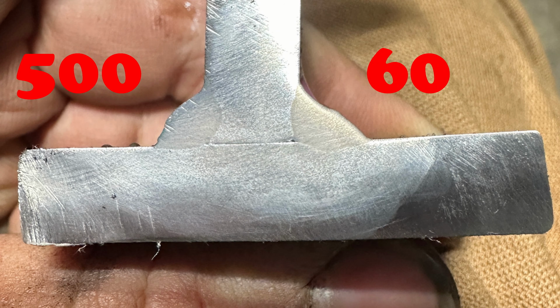Now this picture is somewhat misleading due to the angle, but to the naked eye, they look very, very similar. Now the 500-degree preheat has a little bit more penetration or more or less sidewall fusion into the upright plate, but the room temperature has more in the bottom plate. So it's kind of a horse apiece right here. If I had to pick a more perfect bead profile between the two, I would say that the room temperature I like better simply because it's more consistent in fusing to both of them.